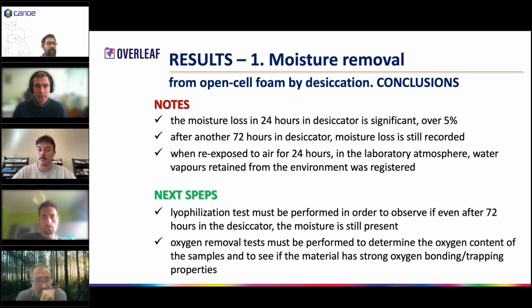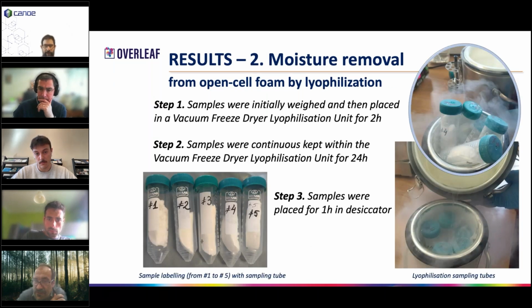So as a next step, we decided to use a lyophilization process in order to observe if, even after 72 hours in the desiccator, the moisture is still present or the moisture can be eliminated. At the same time, we figured out that an oxygen removal test must be performed in order to determine if, after the water elimination, oxygen is still trapped in the material by different physical properties,